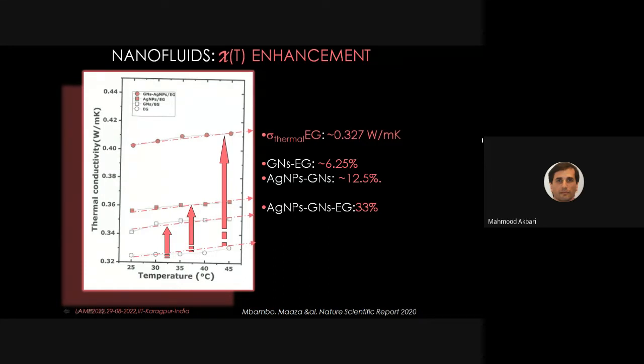And when we take graphene nanosheets at very low concentration in ethylene glycol, it is the second curve, colleagues, the open squares. It moves from 0.327 to 0.347, something like that. Maybe for us it is not high, but it is high in terms of thermoconductivity. It is a good enhancement. Now, if one takes silver nanoparticles at a higher, optimized concentration, yet they will not coagulate, it's the third curve, the pink squares. The thermal conductivity enhancement is around 12.5%.